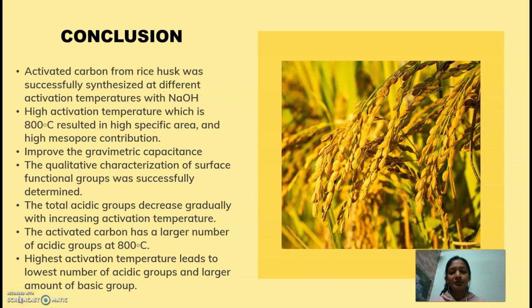As a conclusion, the three objectives that have been stated earlier are achieved. The activated carbon from rice husk was successfully synthesized at different activation temperatures with sodium hydroxide as the activating agent in the range of 650 to 800 degrees Celsius. From this process, it can be said that high activation temperature, which is 800 degrees Celsius, resulted in high specific area and high mesopore contribution.